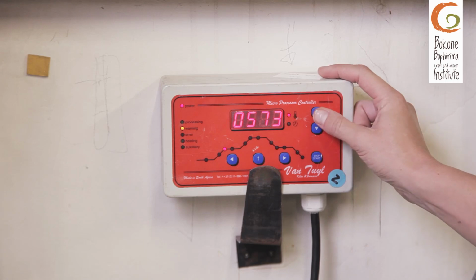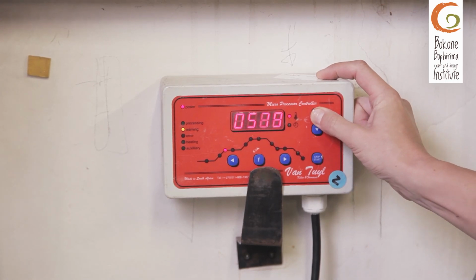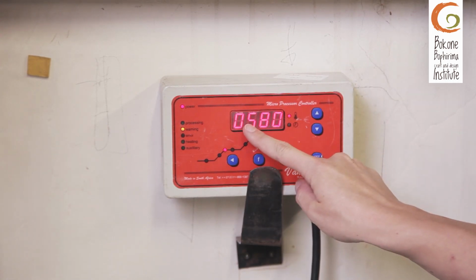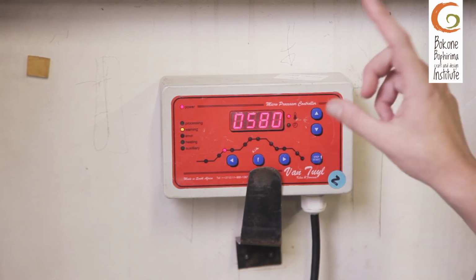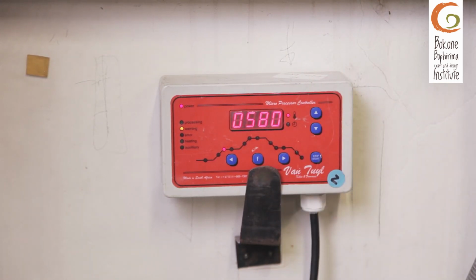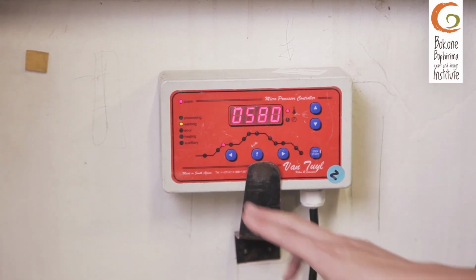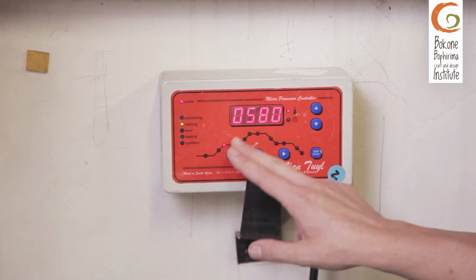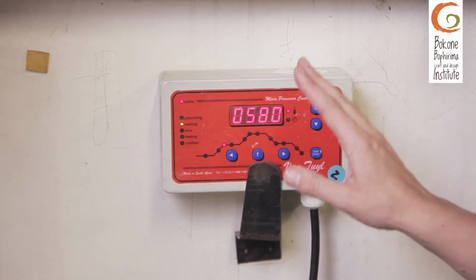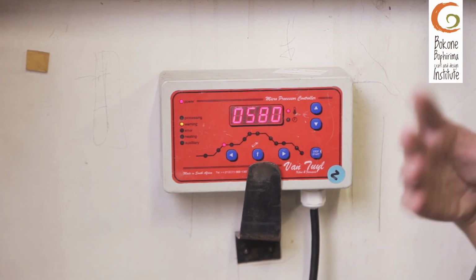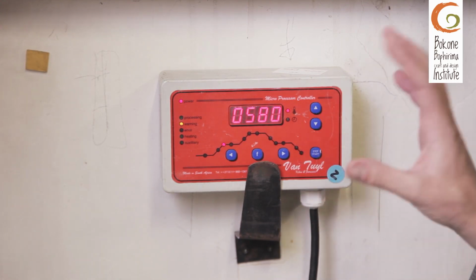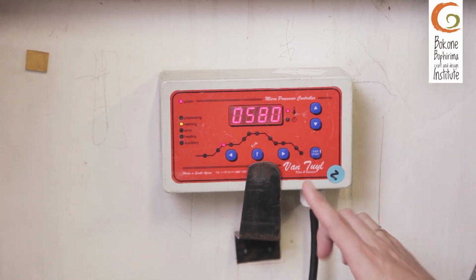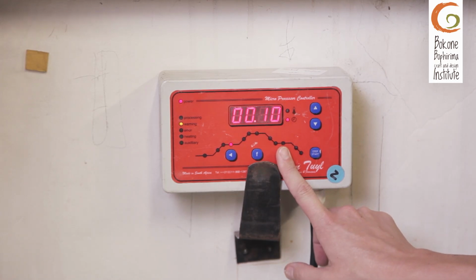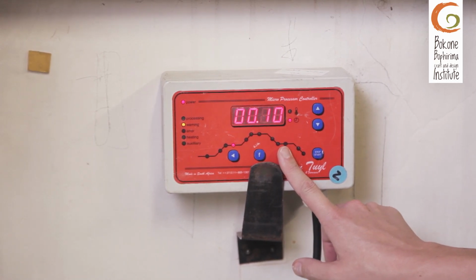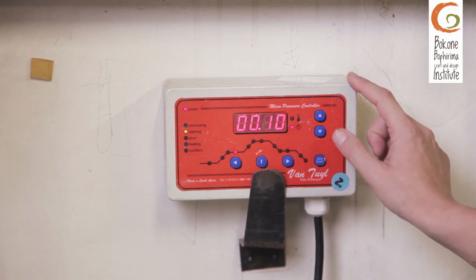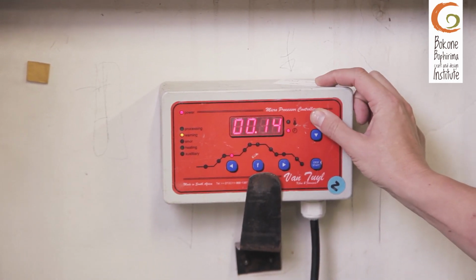And then taking it to the temperature point where my glass is the most fragile. I'm then taking it up to 580 because from 580 to room temperature, my glass is fragile. So I need to work with this process very slowly. I am then going to hold that temperature for 10 minutes. Actually, no, I'm going to hold it for 15 minutes.